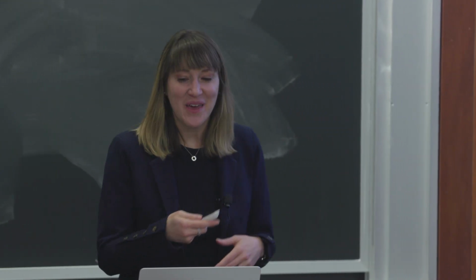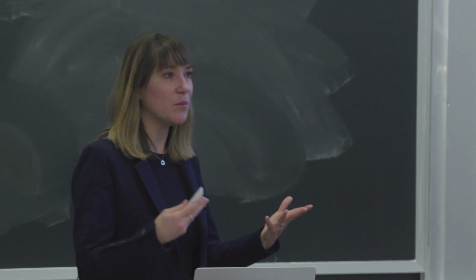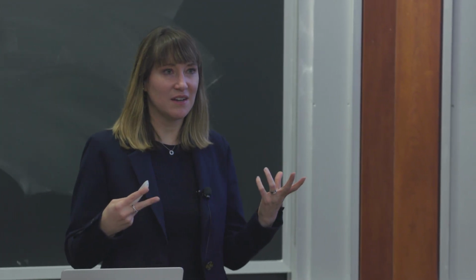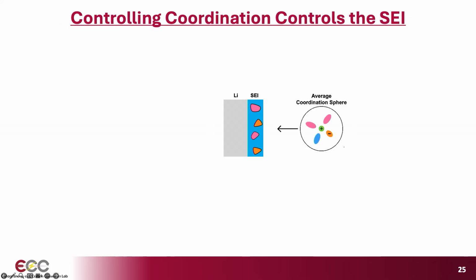Okay, so once we fully understand which SEI we are trying to build, how do we actually do that? So it's long been known in the battery field that the species that are coordinated to the lithium cation are those that are promoted to be most likely to participate in SEI formation. And this is actually really relevant increasingly as we have more complex electrolyte designs. Sometimes there are multiple solvents, sometimes we have additives, there can even be dual salt anions. So we really want to understand how to construct the coordination environment that we want in order to get the